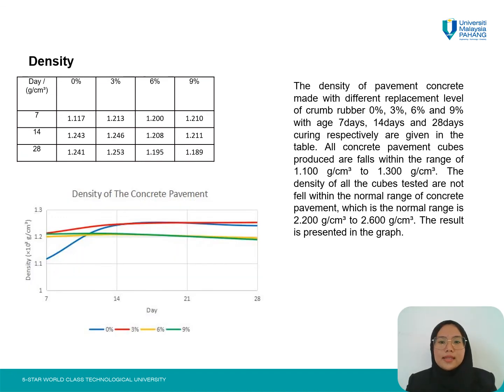Last is the density test. The density of pavement concrete made with different replacement levels of crumb rubber 0%, 3%, 6%, and 9% at ages of 7 days, 14 days, and 28 days curing respectively are given in the table. All concrete pavement cubes produced fall within the range of 1.1 gram per centimeter cube to 1.3 gram per centimeter cube. The density of all the cubes does not fall within the normal range of concrete pavement, which is 2.2 gram per centimeter cube to 2.6 gram per centimeter cube. The result is presented in the graph.